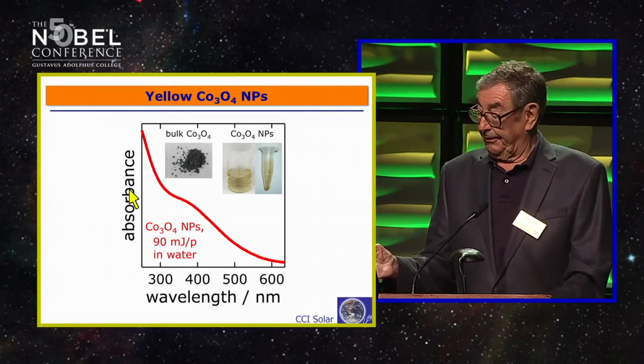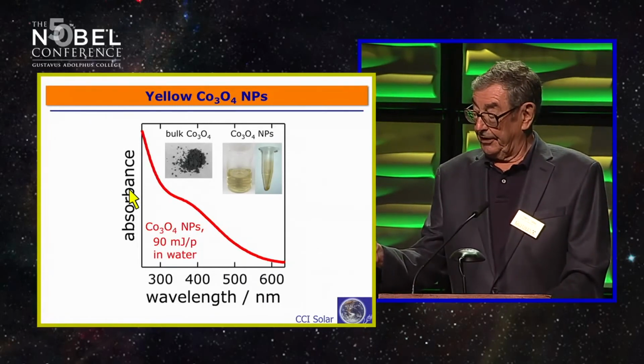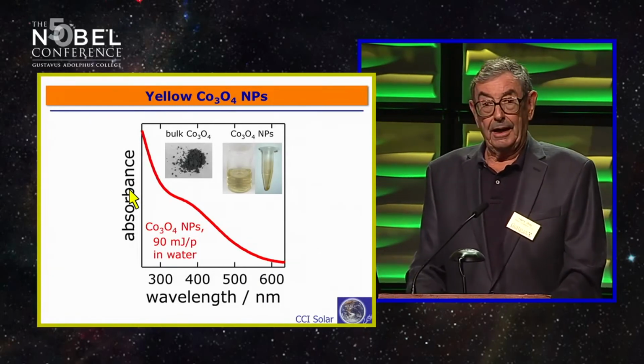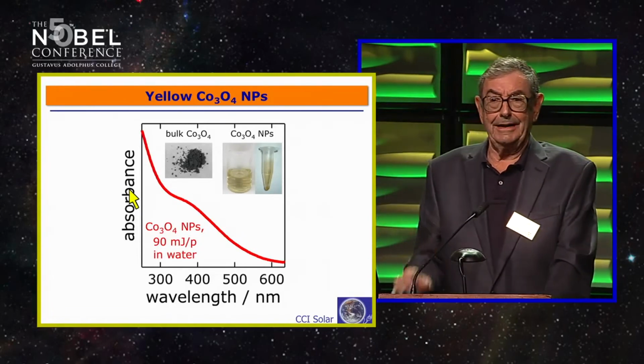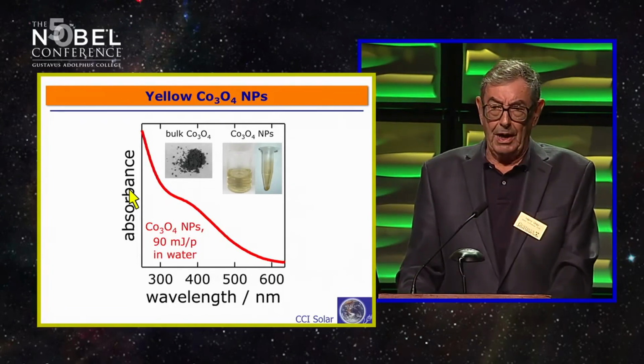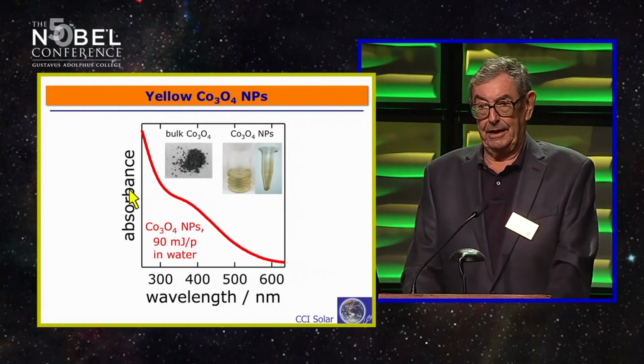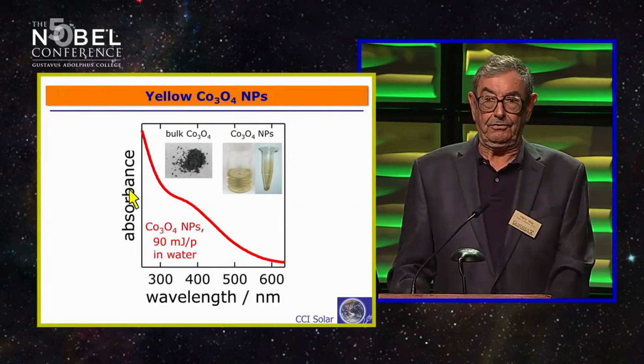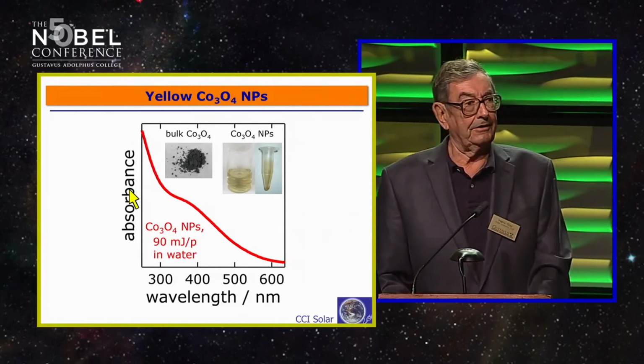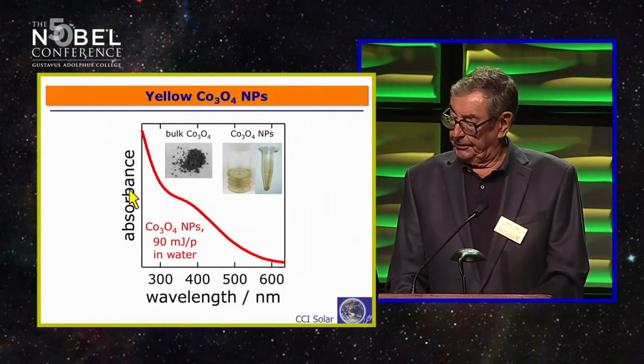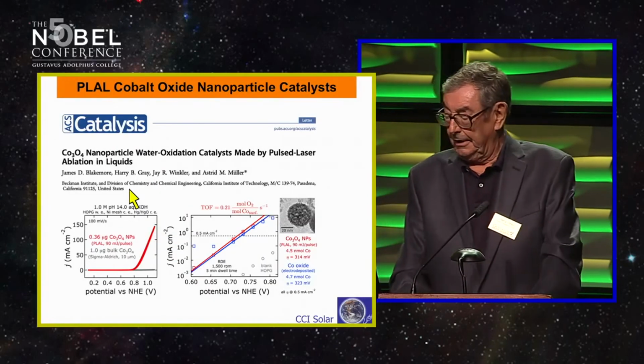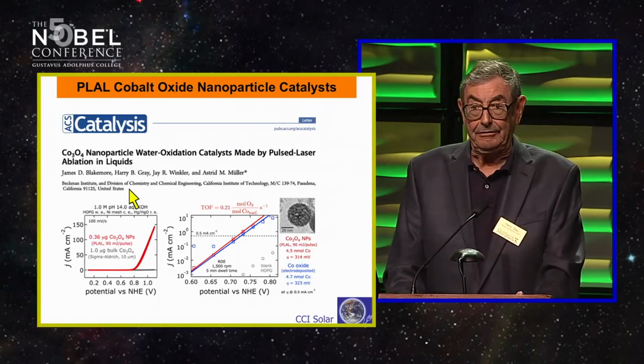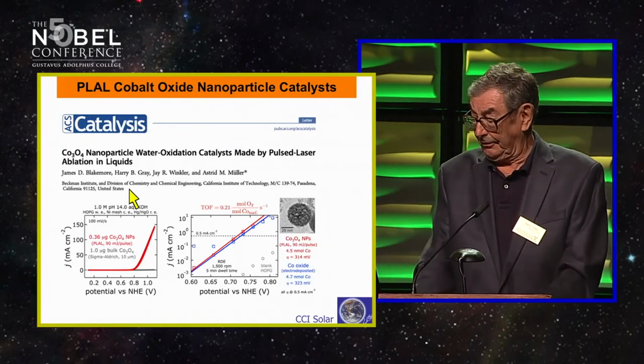They're quantum confined. Bulk cobalt oxide, for example, is black, but our 2.5 nanometer tiny nanoparticles are yellow because they're quantum confined. But let me tell you, they're great catalysts. There's lots of surface area, there's lots of active sites, and we put them on substrates to make photoanodes. They're tremendously active for water oxidation.